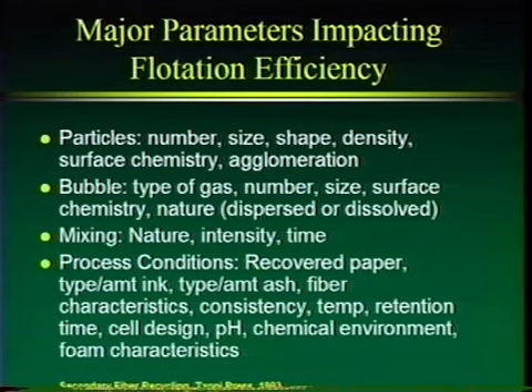And then the bubbles. Type of gas is usually not an issue. It's usually just air. But the number, the size, the surface chemistry, and the nature, whether it's dispersed or dissolved, what size it is, is important. So we've got the bubble considerations. And then also the process conditions. What kind of recovered paper? The type and the amount of ink in that paper. The ash content, the fiber characteristics. Are the fibers very long, or are there a lot of fines? What's the hydrophobicity or the hydrophilicity of the fibers?